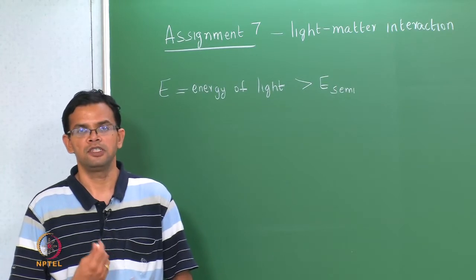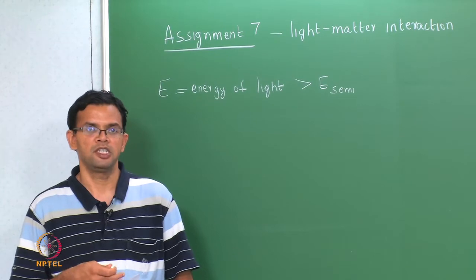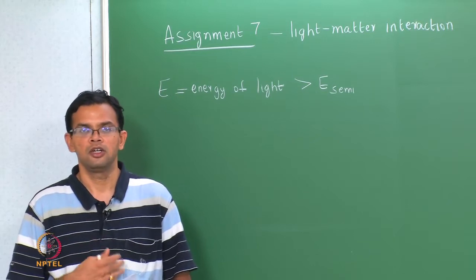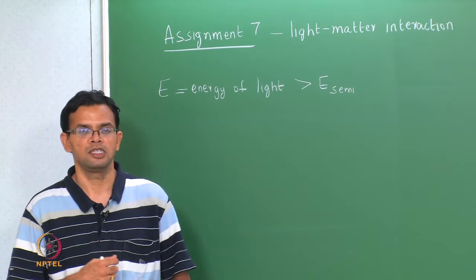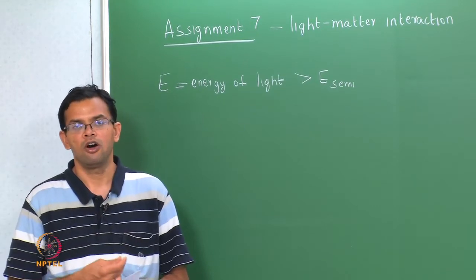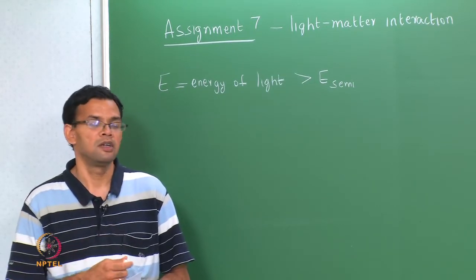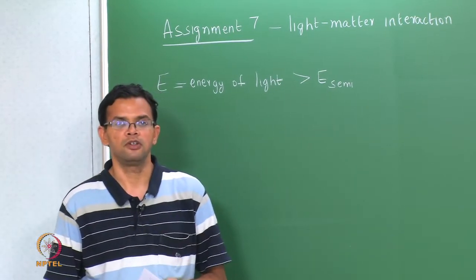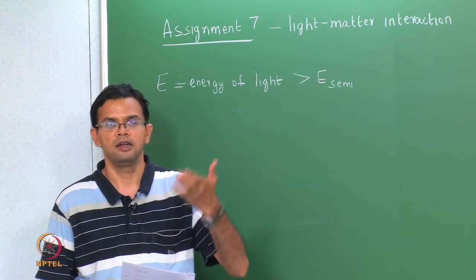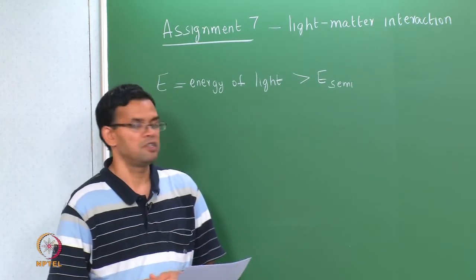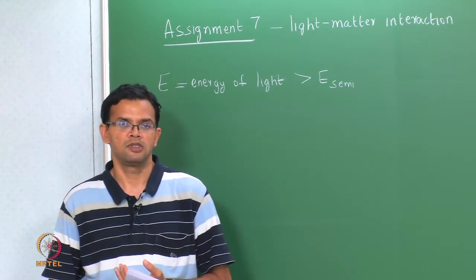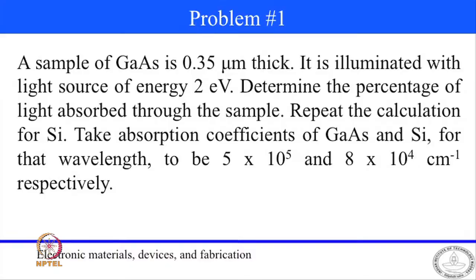You could also have situations where there are defect states or trapped states located within the band gap. These could be located either close to the valence band or to the conduction band, and the interaction of light with the semiconductor causes carriers to excite from the valence band to the trap state or from a trap state to the conduction band. That is why E_semi cannot only refer to the band gap, but could also refer to the energy for a defect state. With this brief introduction let us go to the problems.